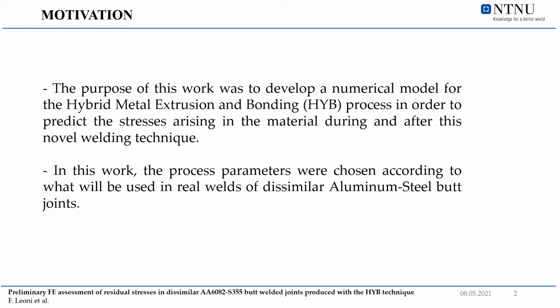In recent times, good experimental results were found for dissimilar aluminum-steel butt welds produced with the HYB technique. So far, numerical models were developed for this process only to study the thermal field that arises during joining of aluminum butt welds, while numerical investigations were still missing for dissimilar metal joints produced with this novel welding technique.